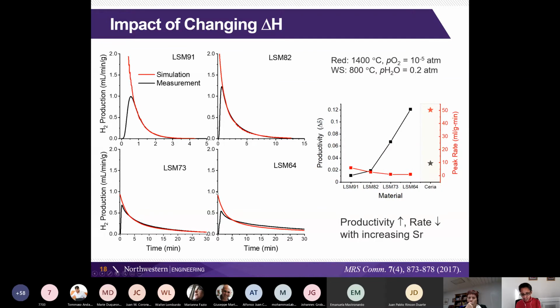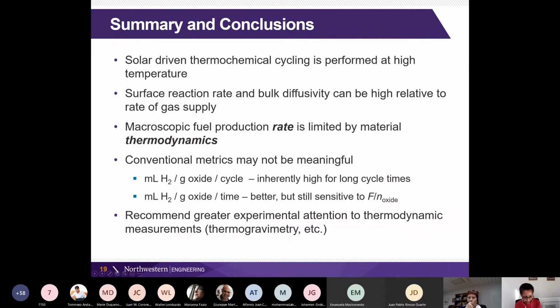And this apparently slow kinetics that has been attributed to perovskites having some feature about them that is kinetically slow really is about a small thermodynamic driving force. So with that, let me conclude and summarize and say, look, solar-driven thermochemical cycling is generally performed at high temperature. And as a consequence, the surface reaction rate and the bulk diffusivity in these non-stoichiometric oxides can be very high relative to the rate of gas supply.